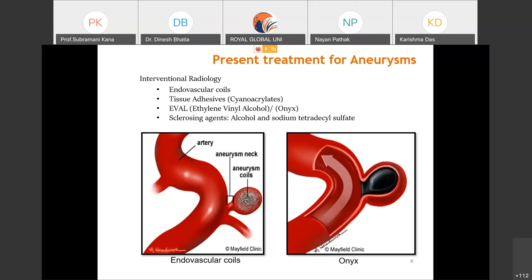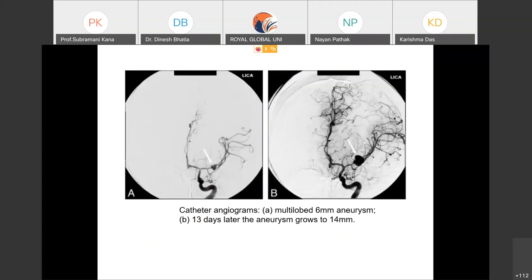Then after that, using shape memory polymer. Because for the FDM technique, you need to have wire, but whatever is available is in the form of pellets, so you have to convert the pellets into wire. Then that wire is used in a 3D printer and you get the shape. This being a polymer, it undergoes two different thermal cycles. One is extrusion, to get from pellets to wire, then wire to the aneurysm shape. So two times when it is processed, the properties suggested by the companies may not be retained. So we need to do a lot of research before we plan to use it.